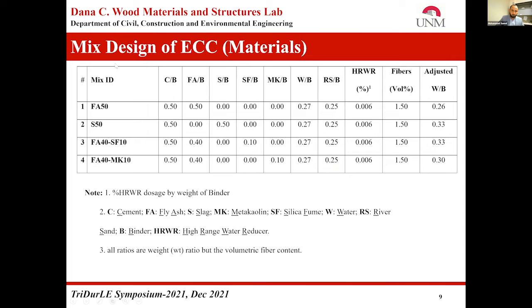So we came up with the experimental work and designed 4 different ECC mixes by utilizing supplementary cementitious materials such as fly ash, slag, silica fume, and metakaolin. And the fiber used was 1.5% of the total volume, and we used polyvinyl alcohol fiber, PVA fiber.